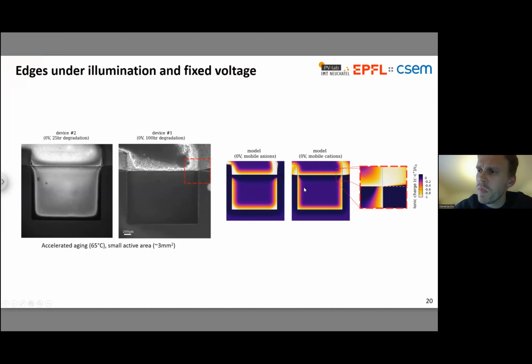So we don't a priori know much about the ion that's migrating here. A good guess is maybe that it's related to halide defects, in which case you'd expect an anion, perhaps. Halide defects, we might think of vacancies or interstitials. So, it could go either way. I simulated both cases of having mobile anions and mobile cations. And it seems like the best match to the pattern is the one with mobile cations.